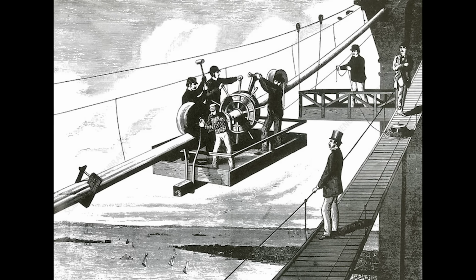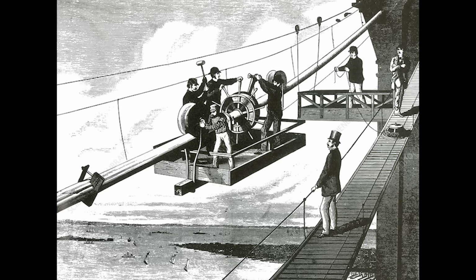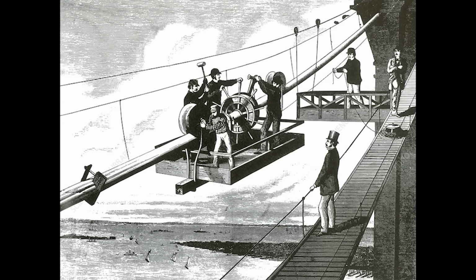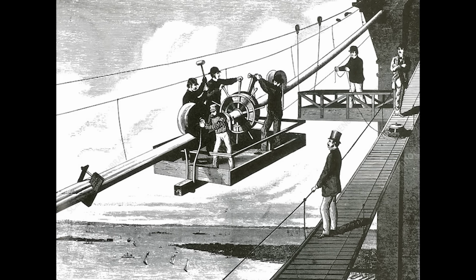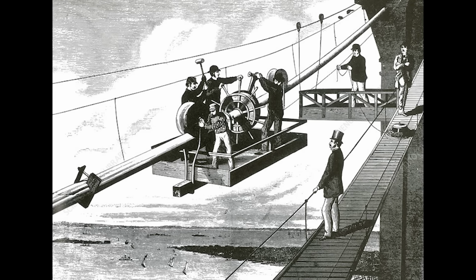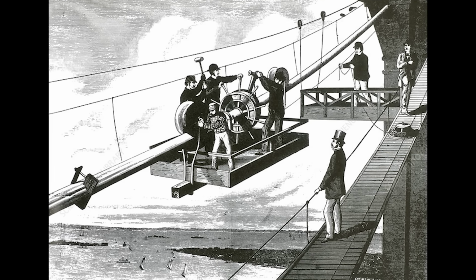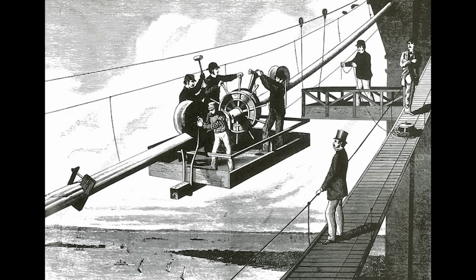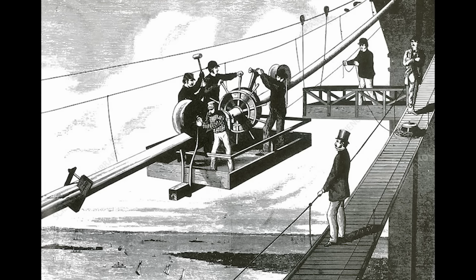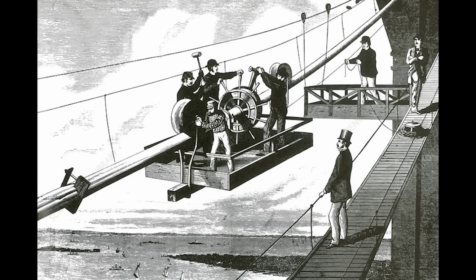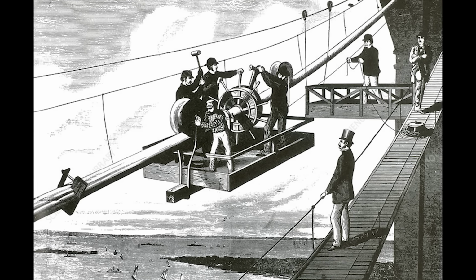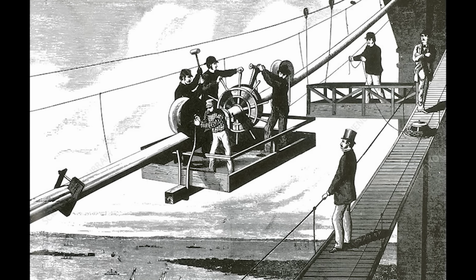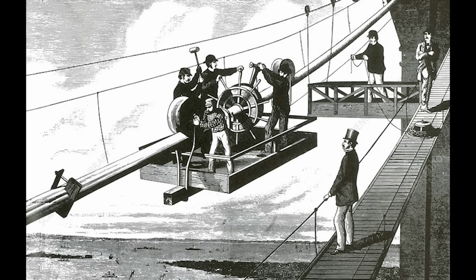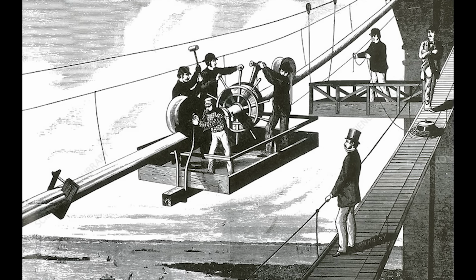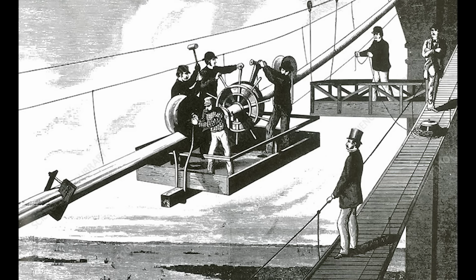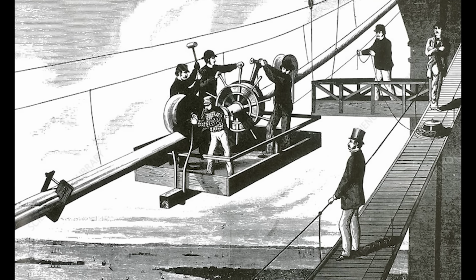Corrosion followed predictable electrochemical rules, and Roebling treated it as a logistics problem. Keep water out, and when water inevitably penetrated the outer defenses, feed the corrosion process with zinc instead of steel. The strategy required multiple barriers working in sequence, each layer buying time for the next. The galvanizing bath created the first barrier. When the wire entered the molten zinc, iron atoms at the steel surface bonded with zinc atoms to form a tough intermetallic layer. This wasn't a coating that could chip off. It was a metallurgical transformation that made the outer surface of the steel wire into something new.